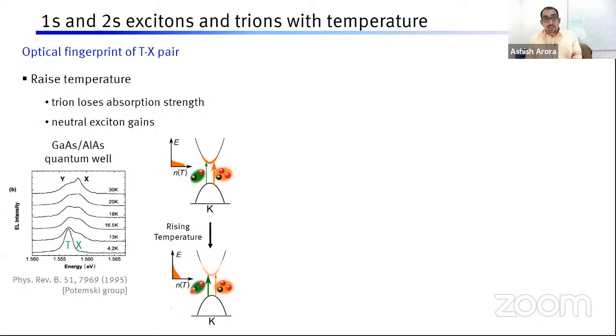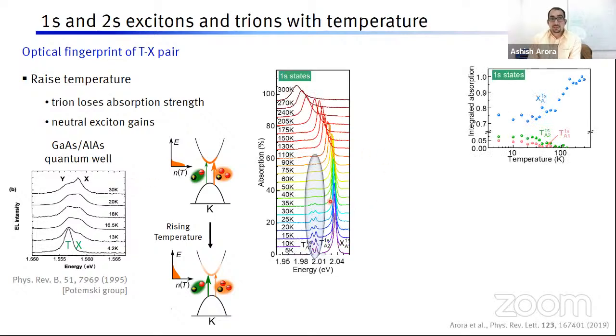However, the probability of creation of neutral excitons increases because you have now empty states and you can excite a very large number of electrons here and can create electron hole pairs now. Therefore, the oscillator strength of trion goes down, whereas that of exciton rises. Now, we test first if it's true in our two-dimensional materials just for ground state trions. Then we go to the excited states.